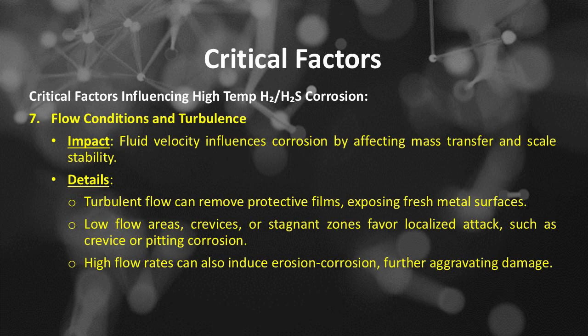Critical factors. Number 7 is flow conditions and turbulence. The flow conditions and turbulence impact: fluid velocity influences corrosion by affecting mass transfer and scale stability. For details, turbulent flow can remove protective films, exposing fresh metal surfaces. Low flow areas, crevices, or stagnant zones favor localized attack, such as crevice or pitting corrosion. High flow rates can also induce erosion corrosion, further aggravating damage.